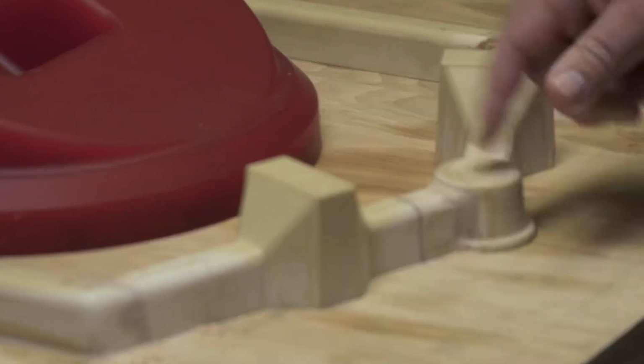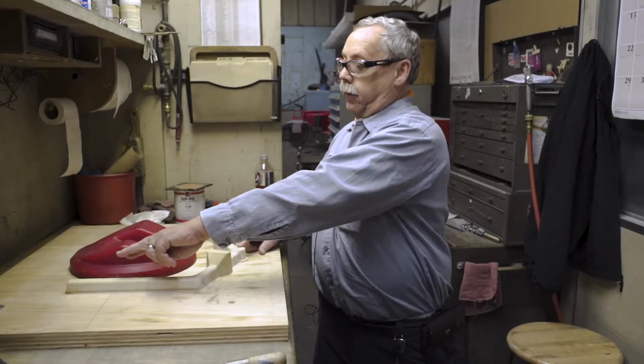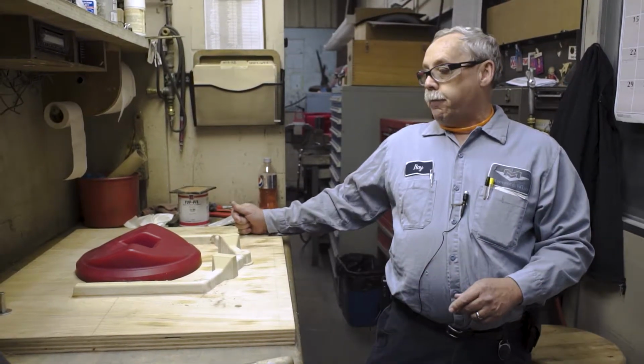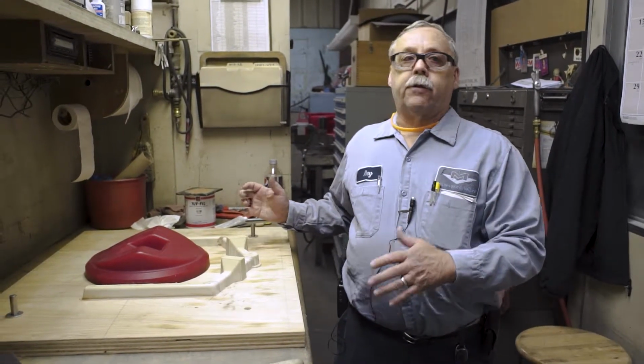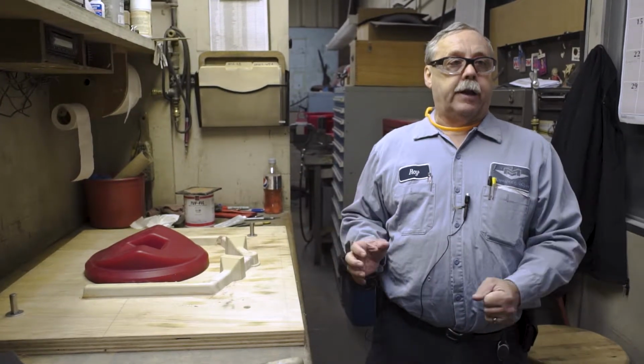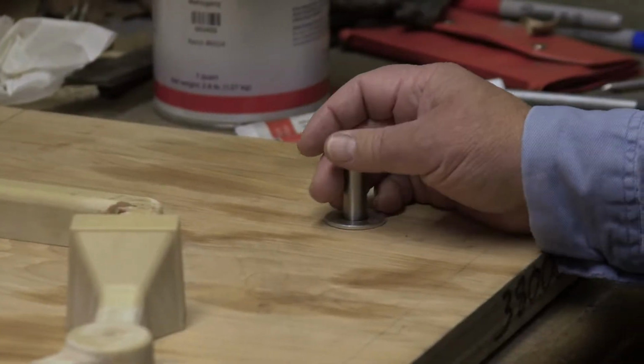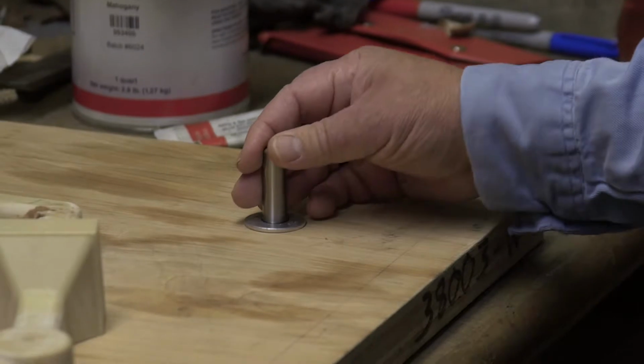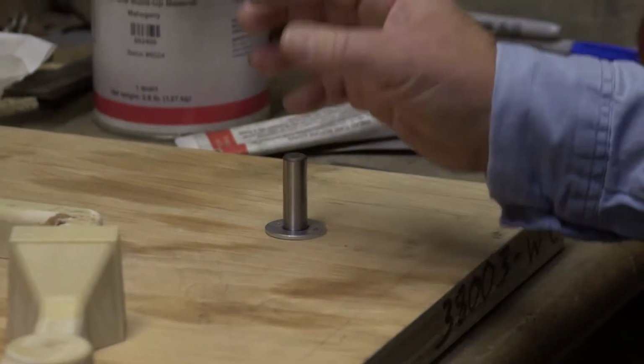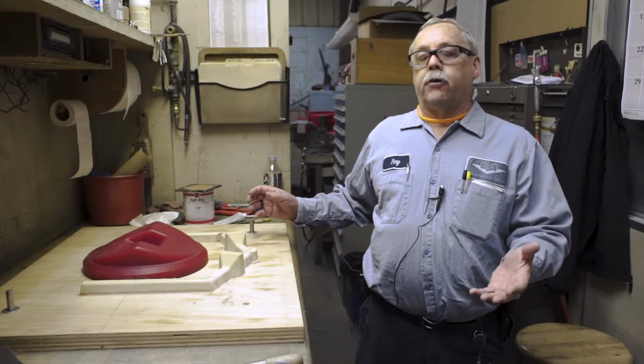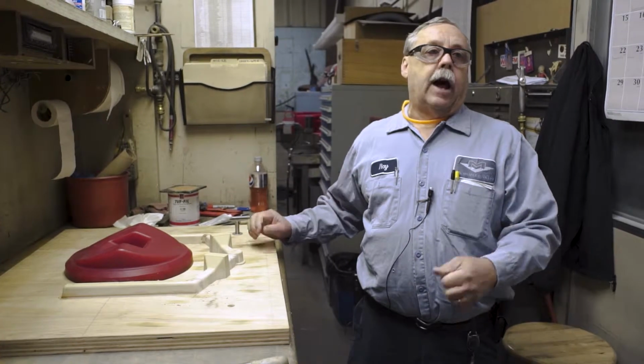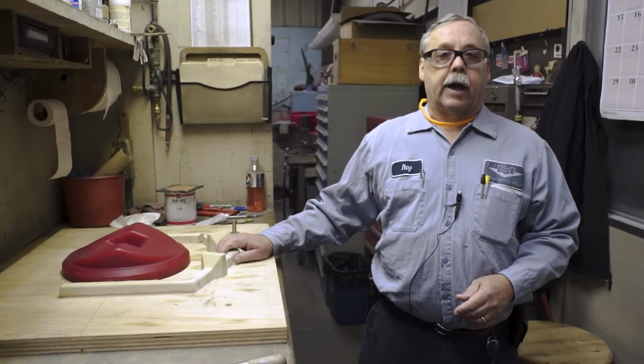There's a filter in here, the metal comes in and goes down this way. We also have the pins here that hold us for the registration from one half to the other half of the mold. We use bushings that are embedded in the sand when we make the mold, and then we put pins in those bushings, and then we use that to align it, so we got alignment when we make the casting.